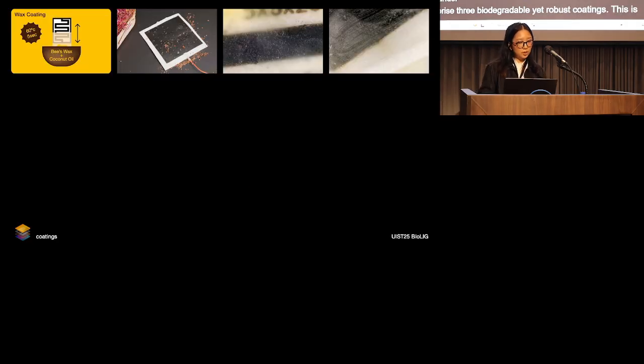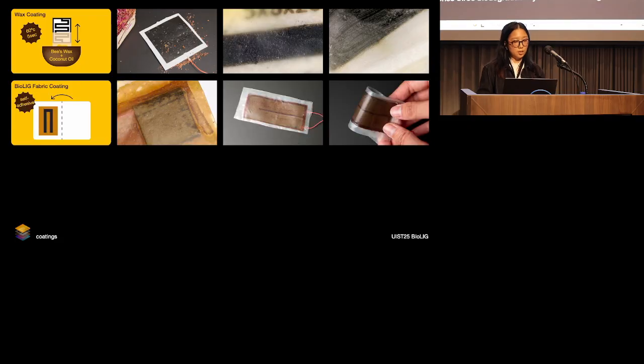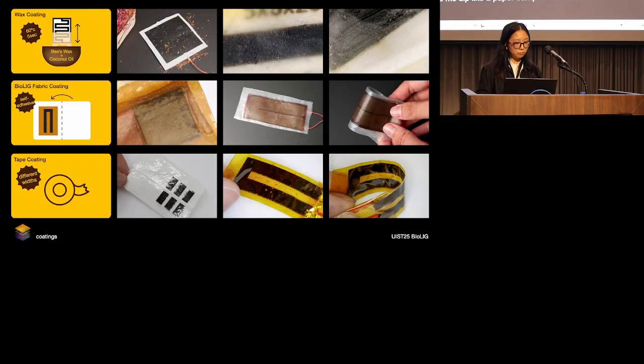Immediately after the carbonization, however, the LIG can be fragile to environmental factors such as moisture or abrasion from the hands. Therefore, we characterize 3 biodegradable yet robust coatings. This is step 3. You can see me dip a paper sample into wax. These coatings make the sensors water repellent, abrasion resistant, and we also tried out a tape for an easy protection.